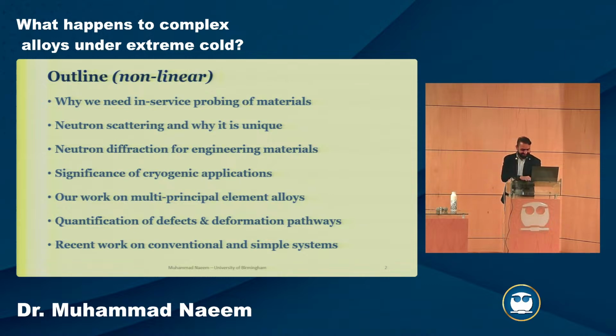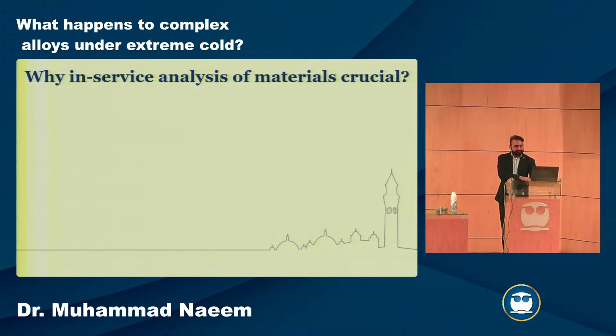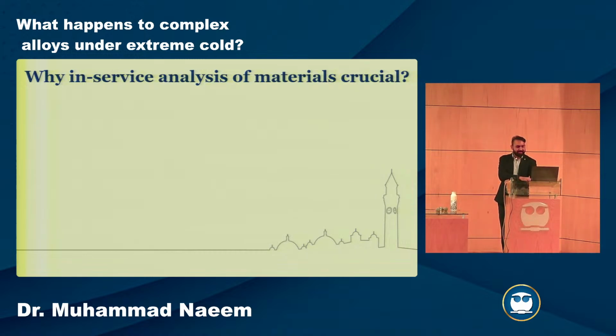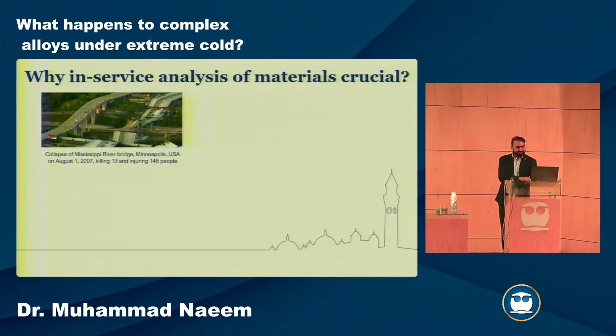So it's fantastic. Okay, so let's see why we need to have in-service analysis of materials, because we want things to keep running. We don't want to encounter any kind of damage. So I'll give you some examples. Hopefully they can convince you that it's important. So this is one example, the collapse of the bridge in Minneapolis in 2007. It was caused by a very thin plate which it was resting on, which really became thinner, like a stress concentration. And it resulted in killing 13 people and injuring almost 150 people.